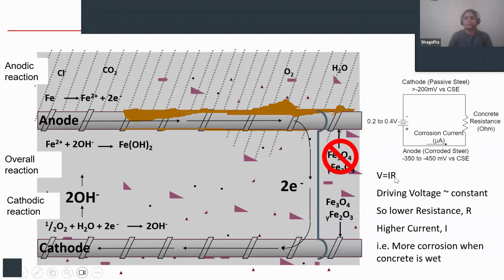So all electrochemical systems basically work on Ohm's law, which is simply V equals IR. Considering the driving voltage is constant, if the resistance is low, that means we have a higher corrosion current. That is the concept behind more corrosion when concrete resistivity is low - in wet structures, the resistance is low, which leads to more corrosion current.